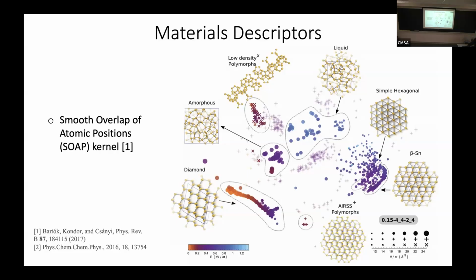Then you unwrap that into a very long vector, and you can project that very large vector into 2 dimensions using PCA or something like t-SNE. And you get some interesting things arising. You notice all the crystal structure types are clustering. For instance, the diamond structures are over here, hexagonal structures are over here, and each point is a different material, and it varies by chemical composition in this cluster and also in this cluster. So the point is that the SOAP encodes something about crystal structure, how the atoms are arranged, and also their chemical composition, which atoms are in the material.